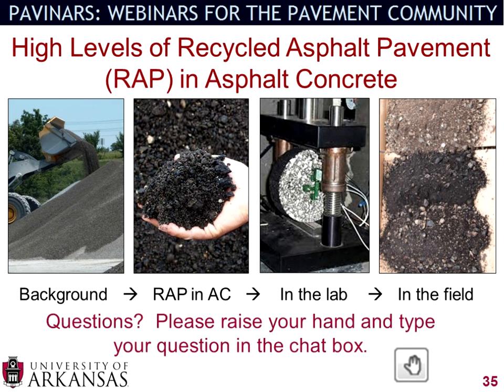And I think that if you're using it in cold mix asphalt, like stockpiling over the winter so you can place it down, unless you mix that with a hotter asphalt material, you're not going to activate any of the asphalt that's on the wrap. So using it at ambient temperatures only, you're not going to get any sort of effective binder replacement, as the Missouri question came up. You're just going to be able to use it as an aggregate. So yes, you can use it as an aggregate, but you're not going to get the benefits of any sort of blended asphalt coming out of it.